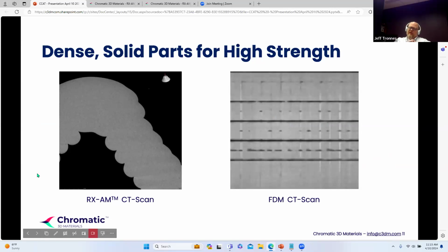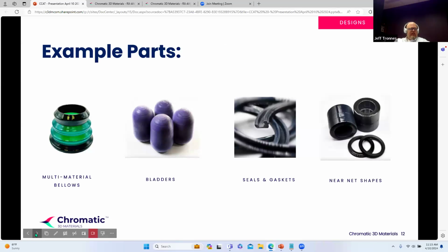And one of the benefits of this material, being the reactive material, is that you do get a very dense, very strong part. On the left here, you'll see a CT scan of our material post printing, compared to an FFF or FDM style print that certainly is not dense. And so you do see the strength and the sealing benefits with the reactive material. I think John's going to take over and talk about applications.